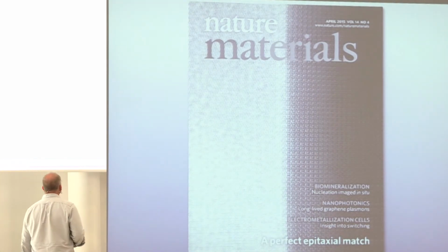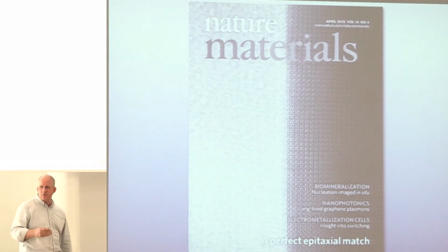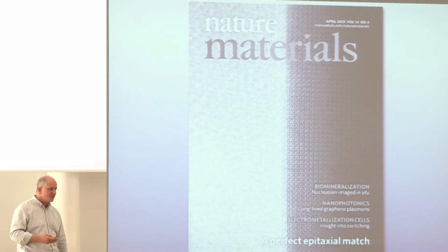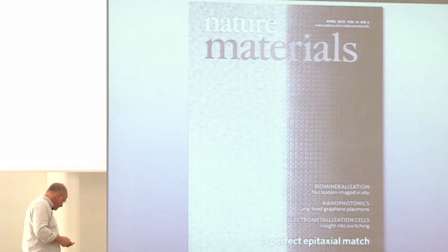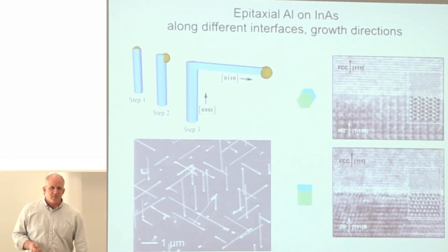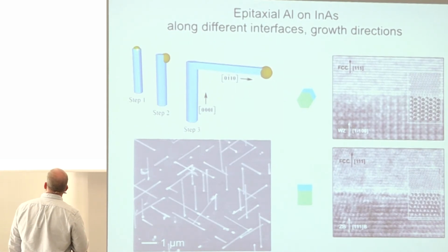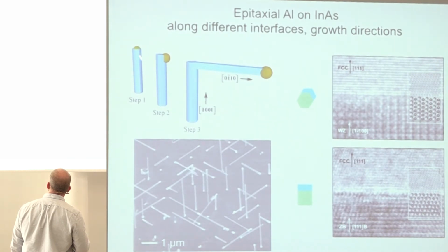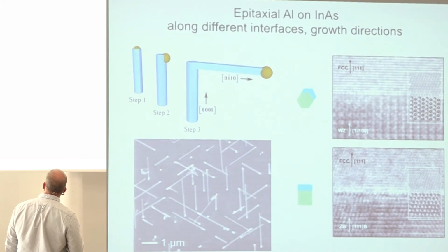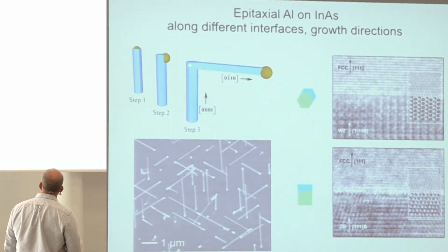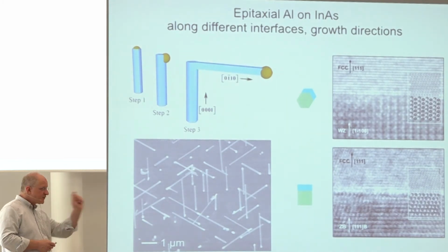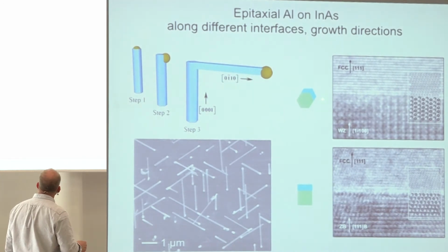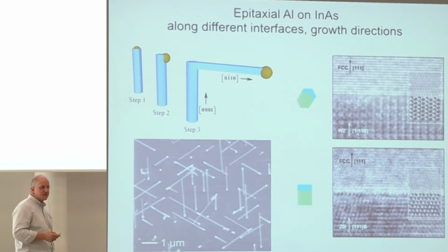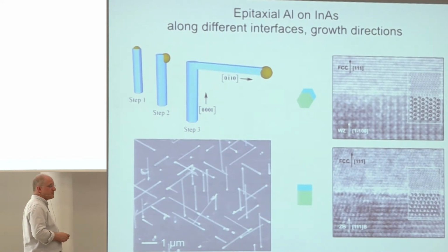But now that there's material that has as intimate a connection between a superconductor and a semiconductor as you can possibly have, you can now revisit some of the geometries that we saw before. The story is even more remarkable than that, because if you look at how these nanowires are grown, Peter has figured out a way in growing these materials that the catalyst particle that is responsible for this upward growth of these can be, by changing the temperature, induced to move around the side onto one of the facets of the nanowire, this hexagonal cross-section nanowire, and then grow out in a transverse direction in a different crystal orientation, moving sideways, and that sideways growth also is epitaxial on its interfaces when aluminum is added to it. So you have two different materials, in effect, with two different amounts of spin-orbit coupling and two different G-factors that both have this epitaxial property.